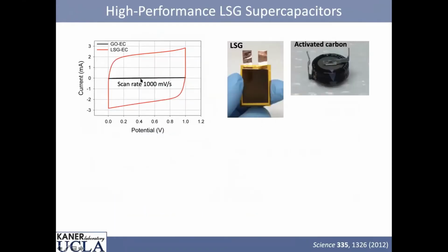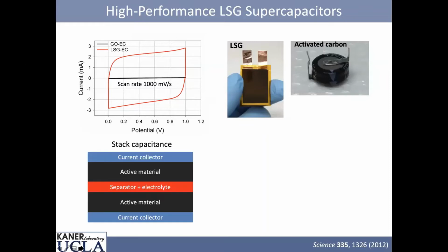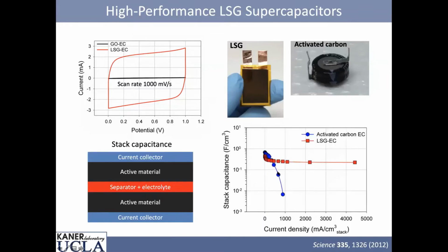Graphite oxide is an insulator. This is a current potential curve. After we reduce it to laser scribe graphene, we get a textbook rectangular wave. It's pure capacitance. And so we can compare it to current materials.